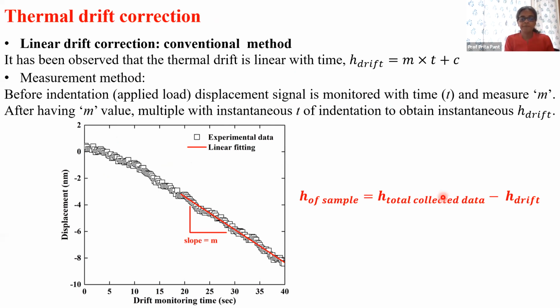Those of you who do nanoindentation know that the instrument itself takes into account that there would be drift. Drift basically means that the tip is going to move without you wanting it to move. It's not an imposed displacement or an imposed load. It's just going to move on its own. And that displacement needs to be corrected from the total displacement. Otherwise, it'll give you erroneous results.